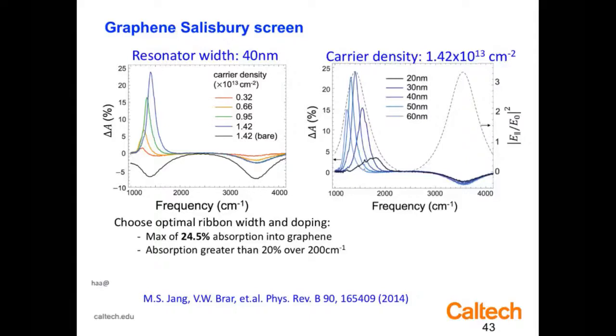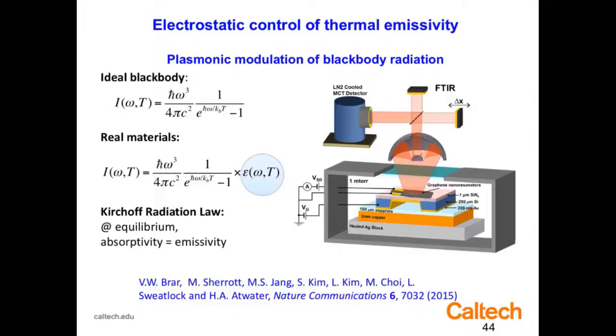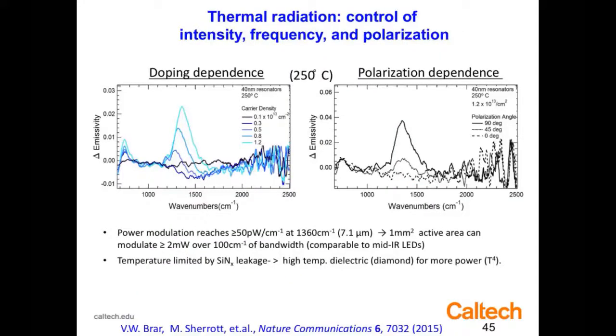We were able to show also that if we heat this up, we could show not only tunable absorption, but the obvious inverse, which is that this exhibits a tunable thermal emissivity. Normally, we think about the thermal emissivity as being a sort of constitutive property of matter. But this is now showing that we can apply a thin layer on the surface of a material and electronically change its emissivity. In other words, at constant temperature, we can change the amount of thermally radiated power. Normally, we change the amount of thermally radiated power by heating something up. And this is at constant temperature. So we showed that that's the case, that as we more heavily dope these graphene ribbons, they become better emitters, that the amount of radiation goes up.